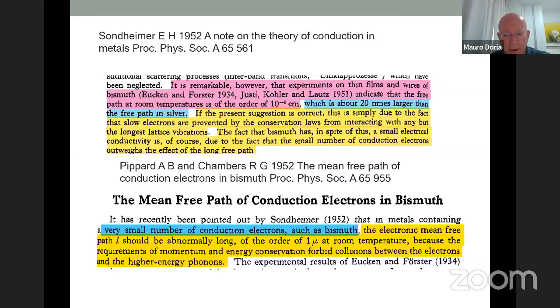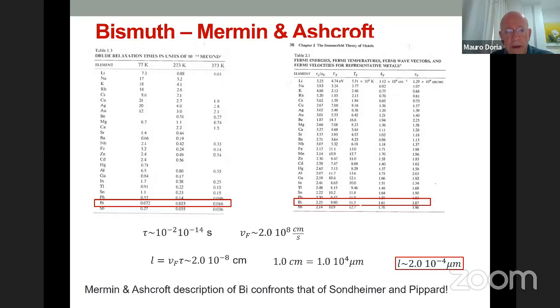In my opinion, which is an opinion, in bismuth somehow you have the momentum of the carriers associated to the spin in such a way that if you want to flip momentum in collisions, because that's what collisions are about, you change the momentum of the particles, but in bismuth this is forbidden, because you have to change also the spin, because the spin and momentum are correlated. That's my opinion. This is what leads to this high free path.